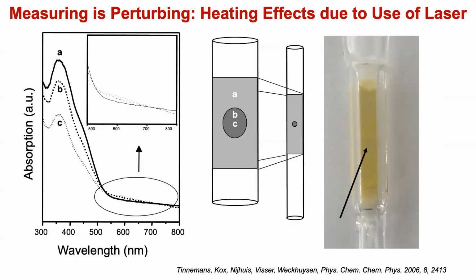How can we also detect that? Well, another thing is that the spot is very important. Here I show you A, B, C. Now, A is where the laser hits. For B, you move out, and then you see the UV-vis. Now that's interesting. You have two techniques. The UV-vis spot is actually broader than the laser, and you measure the effect the laser has on the UV-vis spectrum.